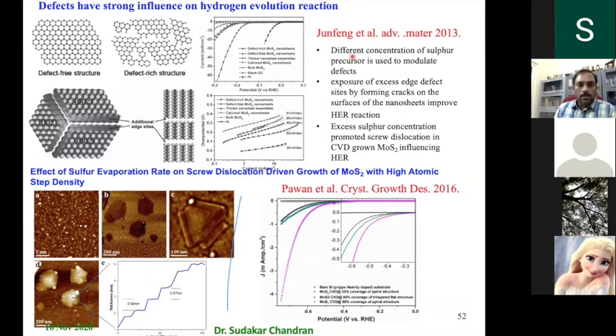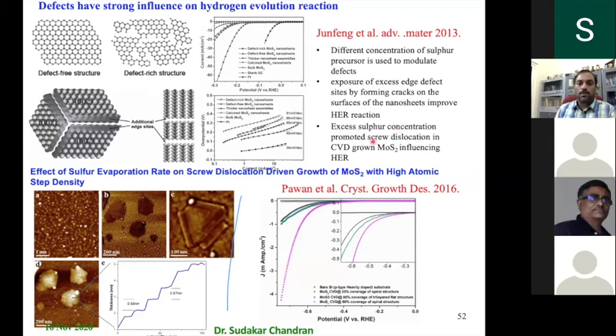In another study, it is also important that molybdenum disulfide is used in water splitting and other applications. The defects are shown to have a strong influence on the water splitting capability. Excess sulfur, whenever you have it, is shown to promote screw dislocations, especially in CVD-grown samples. Therefore, it influences the hydrogen evolution reaction in the electrochemical cell. So it is a very interesting study of how defects can be used to tailor the properties.